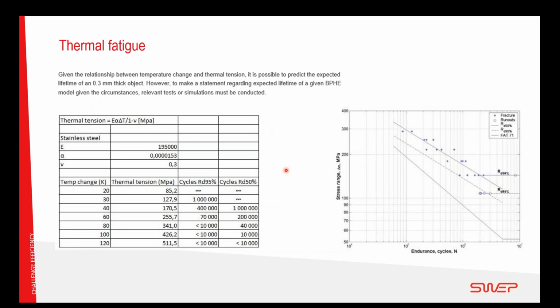When it comes to the thermal fatigue, as a basis for this, we're looking at the material properties. We then look at a 0.3 millimeter thick object, and that's also representing the channel plate thickness in our heat exchangers. And then we look at the temperature change and what allowed tension you can accept in the material. So we can see here that when you are above 120, the lifetime of the material is very low. It will break quite fast. And below 60 Kelvin temperature difference, when you're running a thermal shock, you are then very well increased in lifetime. So this is the data we have then used for our thermal fatigue testing.